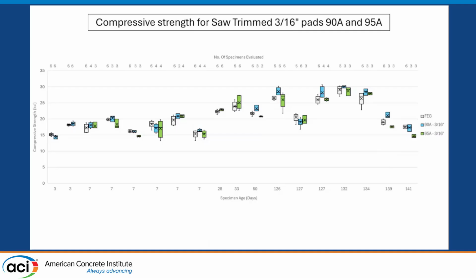And so here's a box and whisker plot, which shows the compressive strength in relation to the saw trimmed condition. On the top x-axis, you can see the number of specimens we evaluated per test, so this ranged between 3 to 6 specimens. And on the bottom, you can see the specimen age in days, and on the y, you can see the compressive strength in KSI.